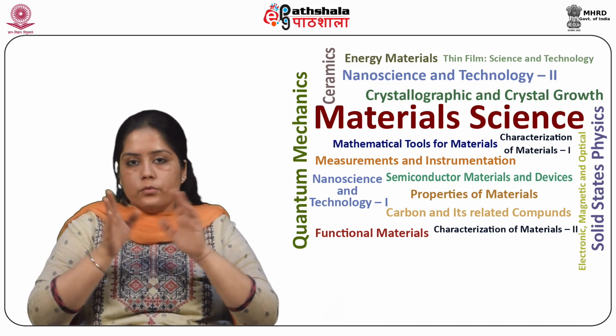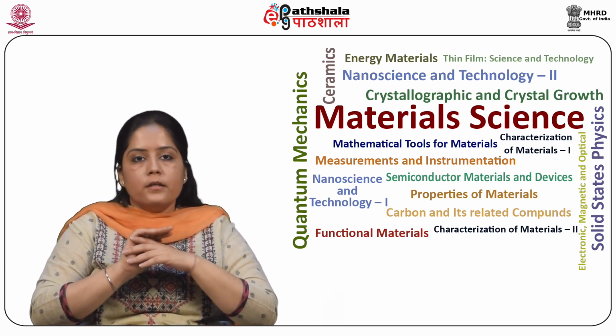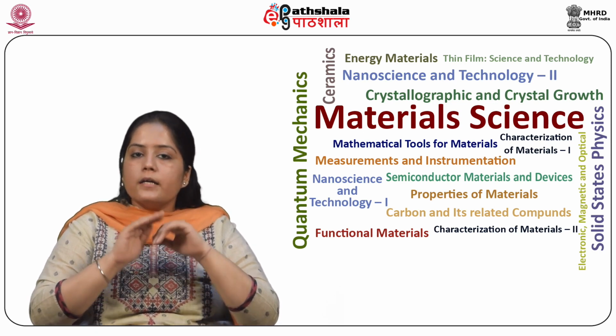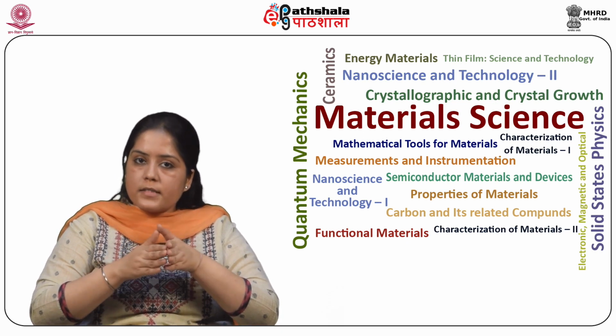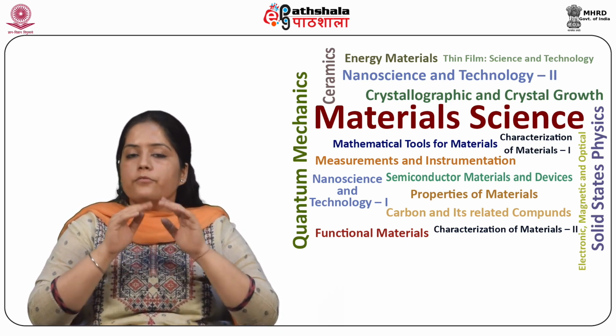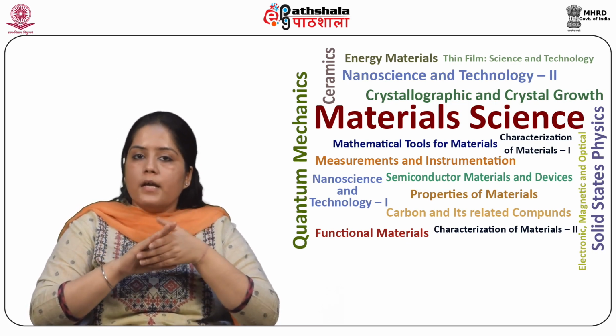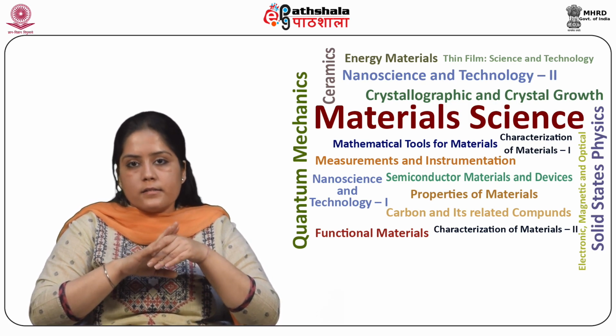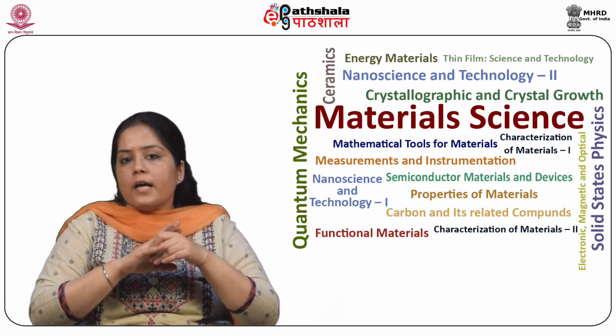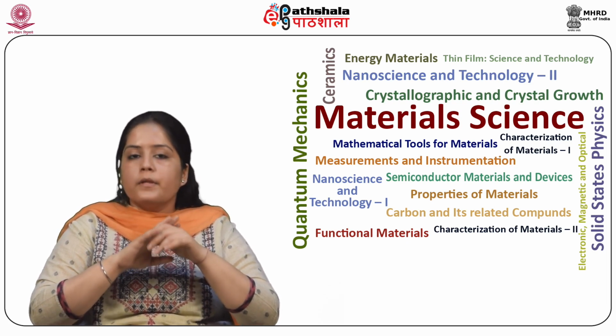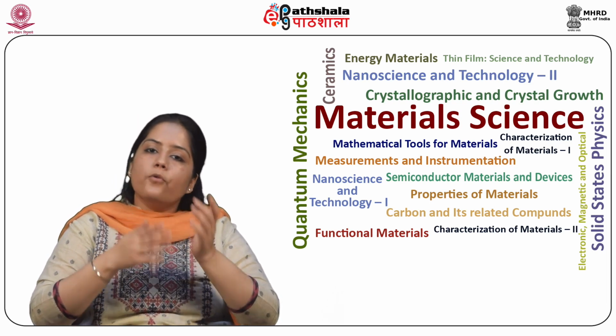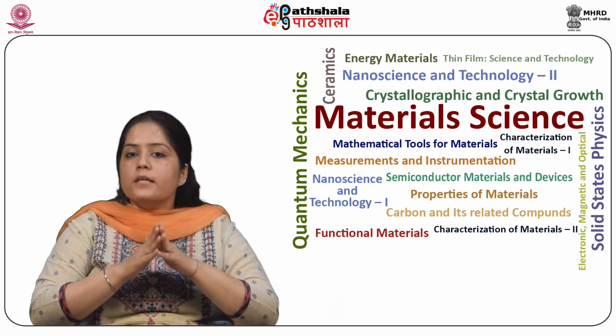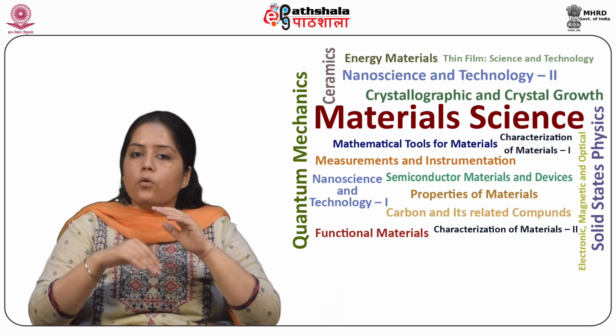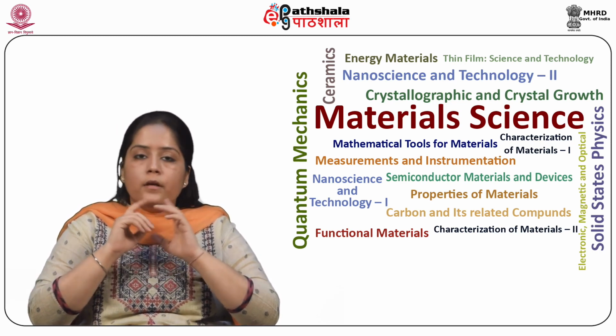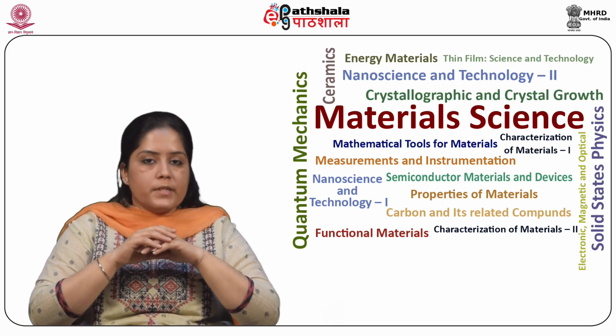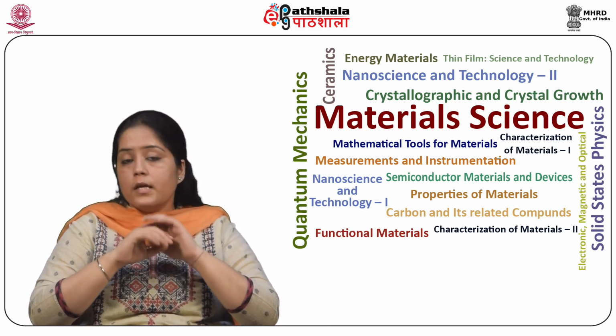Among various dopants used, iodine and bromine can yield high conductivities, but they are unstable and slowly evaporate from the material. On the other hand, use of organic acids such as trifluoroacetic acid, propionic acid, and sulfonic acids yields polythiophenes with rather lower electrical conductivities. However, the environmental stability of these compounds is superior.